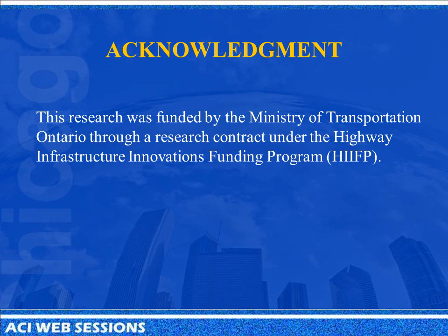The environmental tests, the freeze-thaw and the moisture tests, were the installations done in accordance with AC 308? Not the loading, but the actual installation? Or was it done under a different criteria? Are you asking about the anchor installation itself? Yeah, so moisture installation would be the saturated concrete installation test within AC 308. But the moisture was introduced post installation of the anchor. So we're not testing the whole condition. I think you're asking, but the freeze-thaw test and the moisture test were both installed in a dry condition, and then the anchors were environmentally exposed after they were cured and loaded.